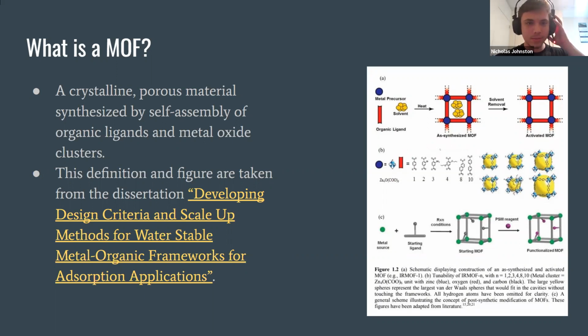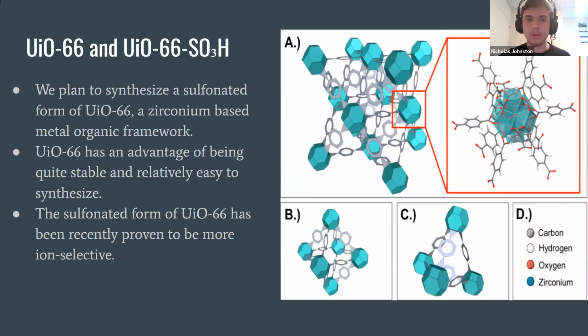Next slide, please. Now, the metal organic framework we are studying is called UiO-66, a zirconium-based metal organic framework. There's a whole bunch of these, but this one is quite stable and pretty easy to synthesize. Before I get into what we plan on doing, the typical synthesis of UiO-66 uses the same amounts of zirconium chloride and what's called terephthalic acid. That's the ligand part. And you use a solvent, I think it's, what is it called again?